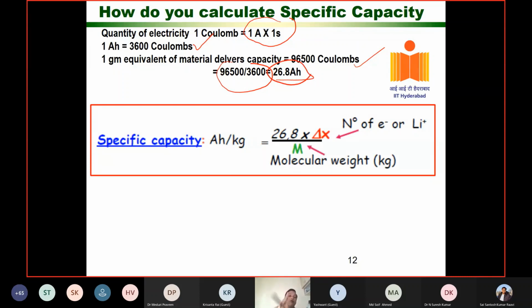That means 1 gram equivalent of lithium can deliver this much capacity. 1 gram equivalent of aluminum can deliver this much capacity. 1 gram equivalent of sodium, 1 gram equivalent of lead can deliver this capacity. So I'm using a term, you see, it's not a gram, it's gram equivalent. The gram equivalent of lithium is 6.94. The gram equivalent of magnesium is 24 divided by 2, which is 12. The gram equivalent of aluminum is 9. So if you calculate accordingly, 1 gram of lithium can deliver a capacity of around 3,860 milliampere-hour per gram.